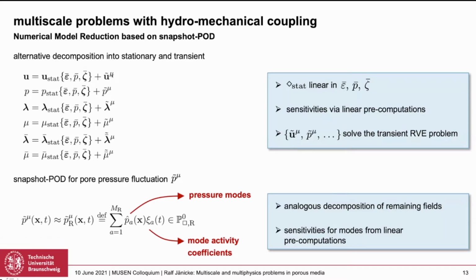Okay, then we only need to solve the transient problem. The treatment of the transient problem is now as follows. We introduce an approximation for this transient pressure field, which is a linear combination of pressure modes times mode activity coefficients. The goal is to have this sum of really low dimension, maybe that we only need a handful of modes. And actually that's possible, but we need a technique to extract the relevant information. And this extraction of the relevant information is done by the proper orthogonal decomposition.